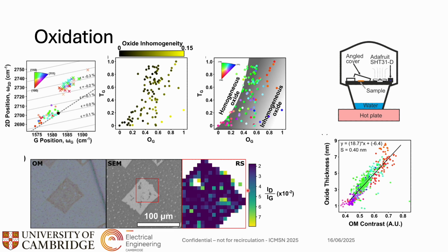orientations in one study. And you can see here, if you zoom in, whilst the majority of graphene in this particular sample has been transferred, the Raman shows a little bit of a different story, with lots of regions having a higher D to G peak. And these reflect regions that aren't necessarily visible in optical or SEM microscopy, but tears, folds, wrinkles, etc., things that are deleterious to the quality as measured of the graphene.